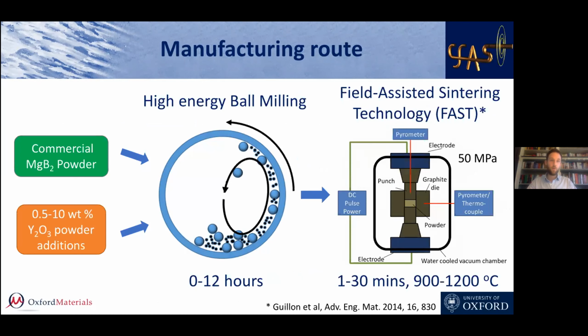We put them in a jar with some steel balls, and we did some high energy ball milling, to mix everything together. And then with these composite powders, we use the field assisted sintering technology. So this is sintering, slightly more advanced than conventional sintering. Essentially we have a graphite die and 2 graphite punches. We put the powder in between, and then we have a lot of current going through the punches, and that goes through the material. And with Joule heating, you heat up your material very quickly, and you also apply pressure. And so that cooks your material and sinters it.